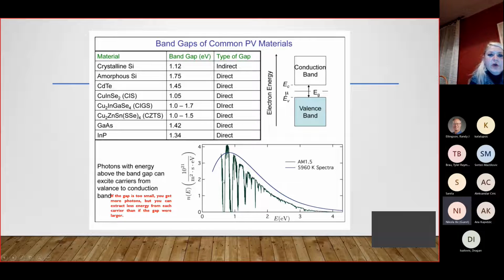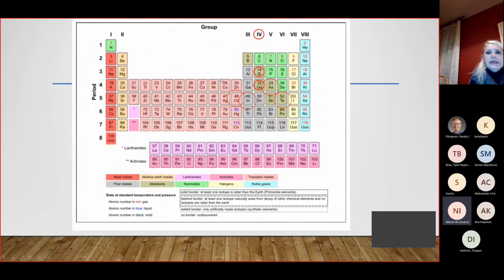And if your band gap is too small, if you go below 1, then you get more photons, but you can extract less energy from each carrier than if the band gap were larger. That's why in this area, from somewhere around 1.5 or so, we choose the semiconductors to have this kind of band gap. Let's keep this presentation only on the semiconductors which are on the market now.